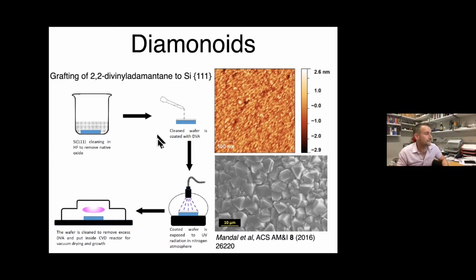So the upshot is that we spent a very long time playing around with it, and we got it to work occasionally, and the problem was on the wafers, you find it's very patchy because the wafer will be oxidizing. So you actually grow well in some places and badly in others, right? And so this is not really very useful. I mean, the interesting thing was that in places that had enormously high nucleation densities, higher than you see with detonation. But the problem is, detonation gives you a very high nucleation across the entire film, right? So just don't bother. So this is why I hate diamondoids. I wasted 2 years of my life on that.